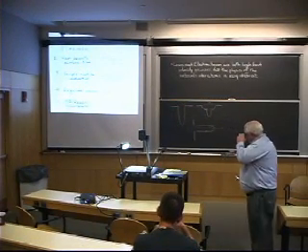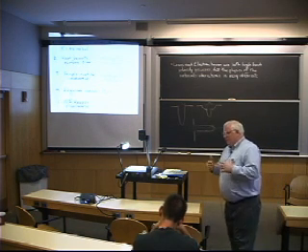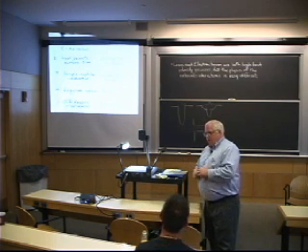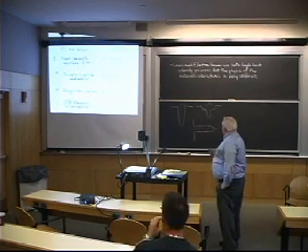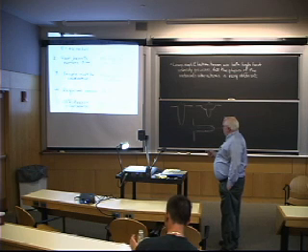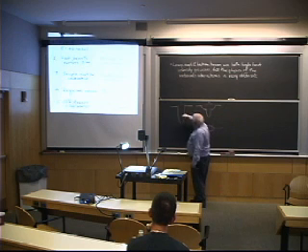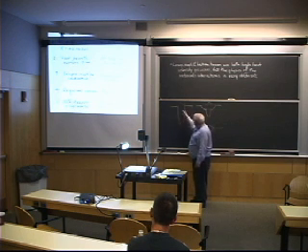It turns out laser, if you had exactly the same heat intensity, you know, 1,000,000 watts per square centimeter, and the same spot size so that you have, let's say, a 10 kilowatt beam, laser and electron beam. It turns out the laser in the atmosphere will give you less penetration than in a vacuum. And the reason is this reactive force of the vapor coming out of here basically is fighting against the atmosphere. If you've got an atmosphere up here, if it's vacuum, it's just going straight out and you get better momentum transfer to dig the hole.